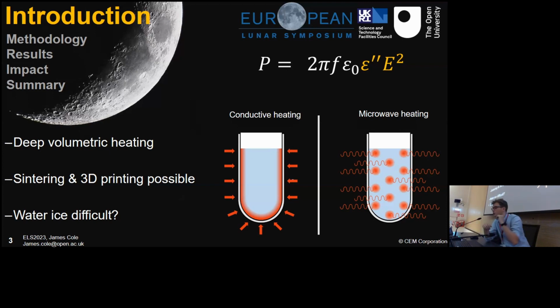The equation on the top highlights the two key factors in all of this. You've got the capital E, which is the electric field, which essentially just means if you put more power into your microwave source, you'll heat up more area or heat up more quickly. And then you've also got your epsilon, which is your dielectric loss factor. It's a material property. It's reliant on frequency and temperature, and is quite different for each material. The important thing to say here is that lunar regolith actually has a very high dielectric loss factor, which means heating is efficient, and that's why it's been used for sintering and 3D printing experiments, as we can get to molten temperatures really quickly using microwave heating.